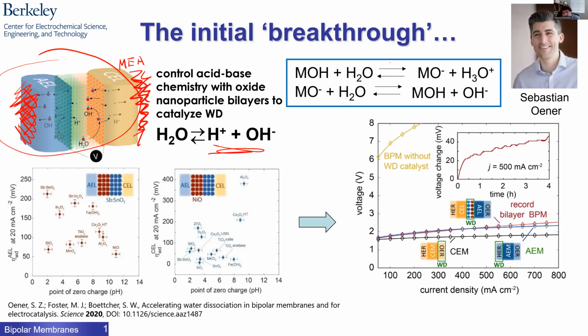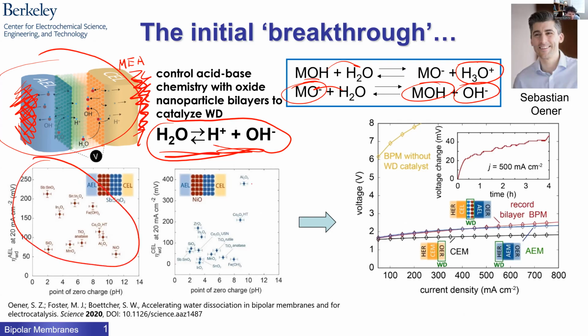kind of proposed that you might be able to dissociate water. He was looking at small molecule or polymer groups dissociating water by this mechanism, and we were going to apply it to metal oxides in the simplest sense. You could dissociate water in 2 steps instead of 1 step. So this is sort of the bulk water mechanism, auto-dissociation. But if I had a slightly acidic metal site, it could donate a proton to water, make a hydronium, and then a deprotonated site, either the same one or a different one, if they communicate, could then abstract a proton and return the metal hydroxide, for example, and make an OH-. So we thought this might be operative. We screened a whole bunch of metal oxides. I'm not going to go through this paper very carefully because we have a lot of better data now that's more mechanistically insightful. But we saw general trends where the pH of the surface of the metal oxide really matters, and you want to match the pH of the metal oxide you use for the catalytic rate.